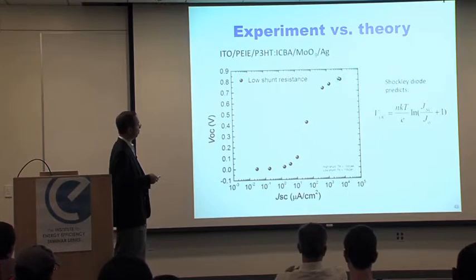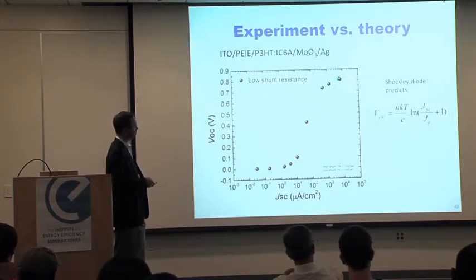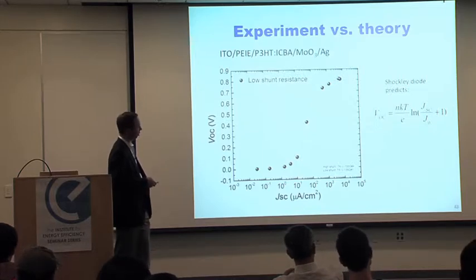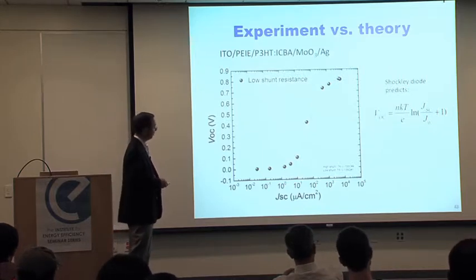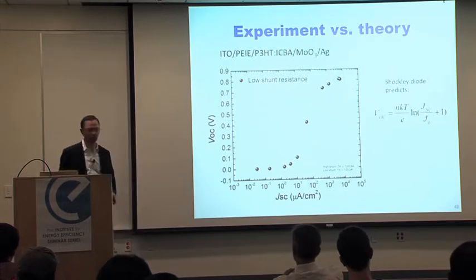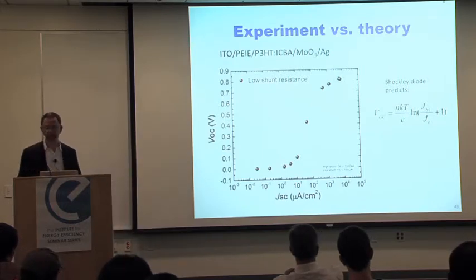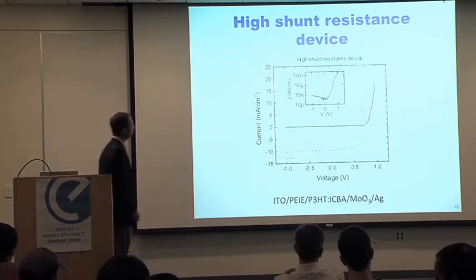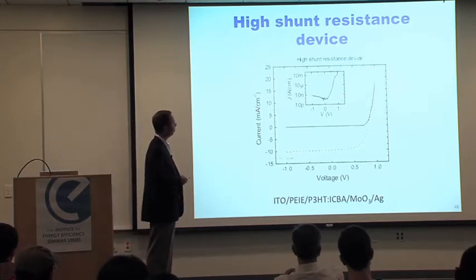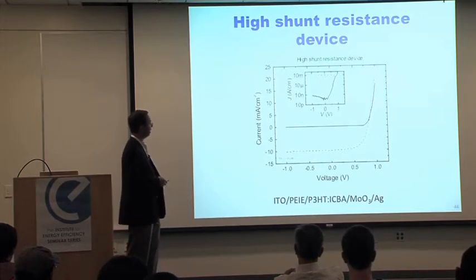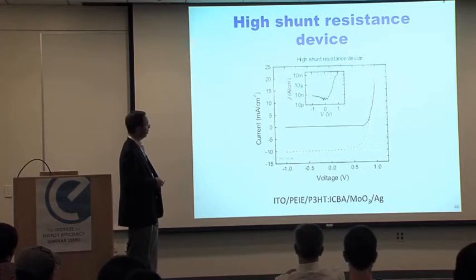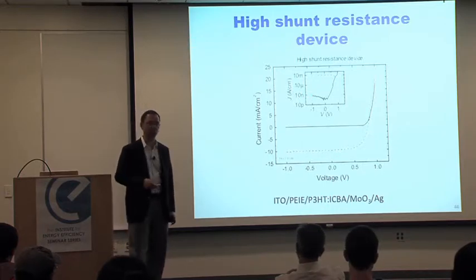And you start to reduce the light by about 2 orders of magnitude. You see a reduction in VOC, as you expect from that simple Shockley model of a diode, you're just inverting it. But very rapidly, things changed drastically. And we were really puzzled by this for a very long time. However, occasionally, and these were really outliers, which initially we disregarded, you would have devices where now, in the dark, in reverse bias, the current was below 10 nanoamps per square centimeter.